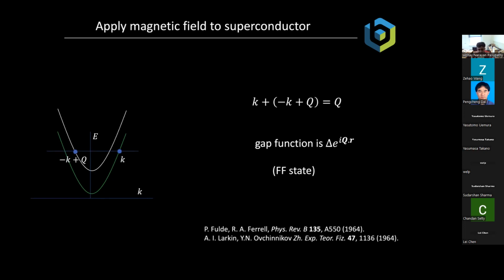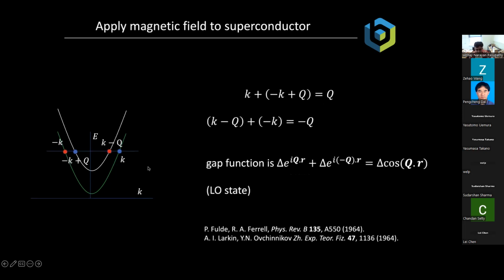Now you can ask yourself, in such a superconductor, what does the gap, what does the superconducting order parameter look like? And the answer is that in this particular case, the superconducting order parameter psi is, once again, a complex number with an amplitude, where the amplitude is delta. But now the phase is no longer a constant in space, but the phase is winding in space. So psi looks like delta e to the iQR. And in the other case, the LO case, this looks like a combination of delta e to the iQR that comes from this guy, and delta e to the minus iQR that comes from this guy. And so you put both together, you have e to the plus iQR and e to the minus iQR, and that is a cosine of QR.